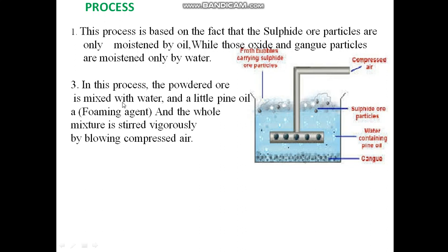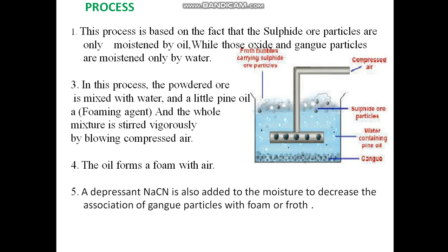In this process, the powdered ore is mixed with water and pine oil — pine oil being the foaming agent. The whole mixture is stirred vigorously by blowing compressed air through the tank containing powdered ore, water, and pine oil. The oil then forms a foam with the air.